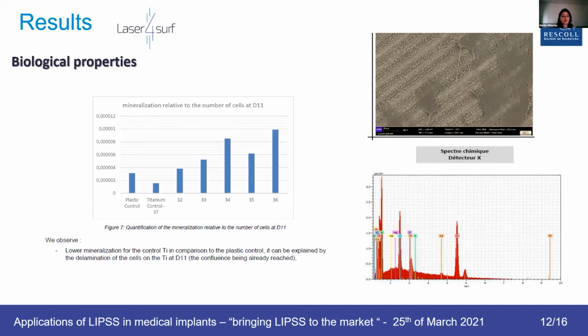We can see we have a great improvement of the mineralization on the surface, and it's even better than a sandblasting surface treatment, which is the 32 and the 33 here. We can improve, compared to conventional treatments, the functionalization of the surface. The cells are able to spread very nicely on the surface, as we can see here in these pictures. And we can even see the formation of calcium crystals on the surface, which is a clear sign of calcification, and this will improve the bone to implant contact.